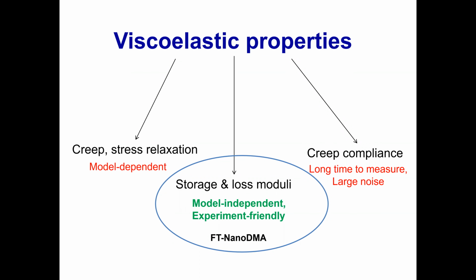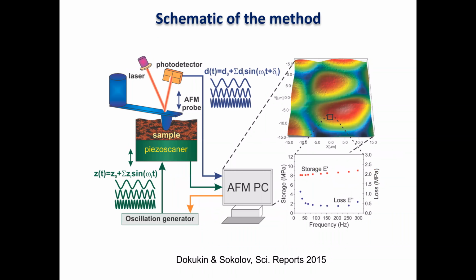So why do we call this FT? FT stands for Fourier transform. It allows to do measurements at multiple frequencies at the same time. So what is this method in general? Dynamical mechanical analysis is when you develop some contact with the sample, and then you oscillate, well, either sample or probe, and see the response. So you have, for example, in this case, oscillation of your sample with some amplitude, and you measure deflection of the cantilever as a function of time.